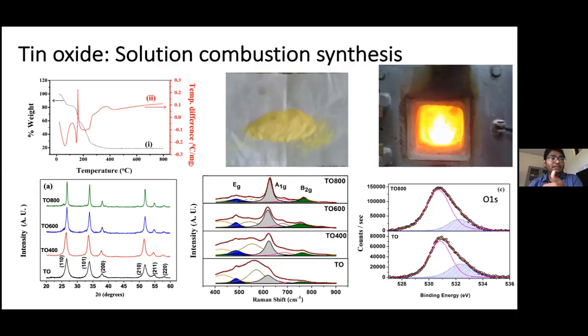And then on the other hand, in the annealed sample, as you can see, it just goes on reducing and reducing in intensity as we went on annealing at 400, 600, 800 degrees. The 800 was somewhat like a bulk crystal, bulk sample. And the 1500 degree, which I did later on, had very sharp peaks with absolutely no defect modes, and so on like that.